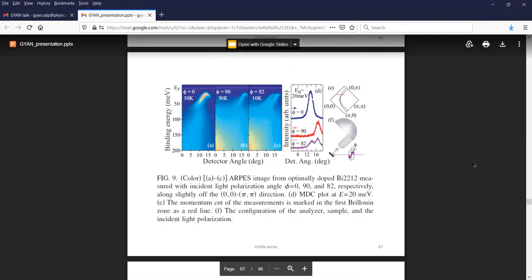In recent times, you can change polarization — polarization-dependent measurements let you, if you have two bands with different symmetries, actually tune them separately. Zero degrees is S-polarized (linear horizontal) and 90 degrees is P-polarized (vertical). At zero degrees you get one peak, at 90 degrees you get one peak but shifted, and at 82 degrees you get two peaks corresponding to the two separate bands. This is shown as momentum distribution curves (MDC).